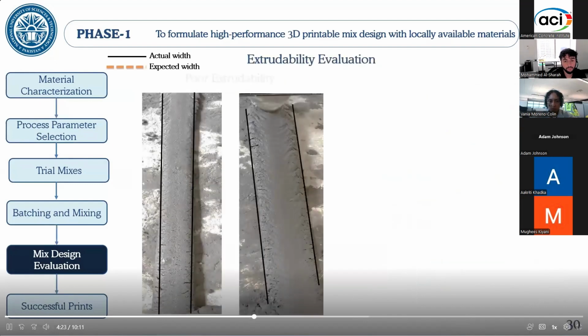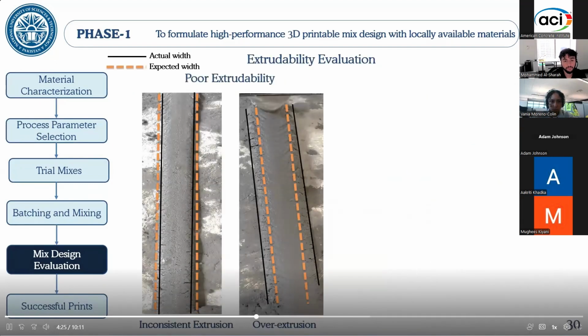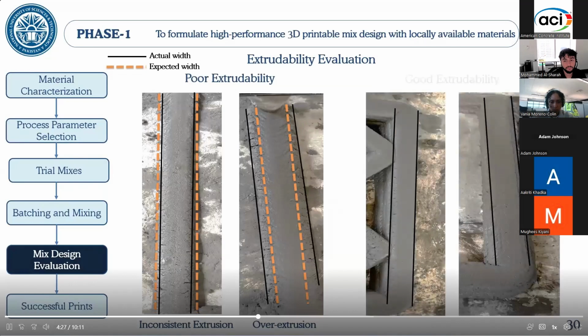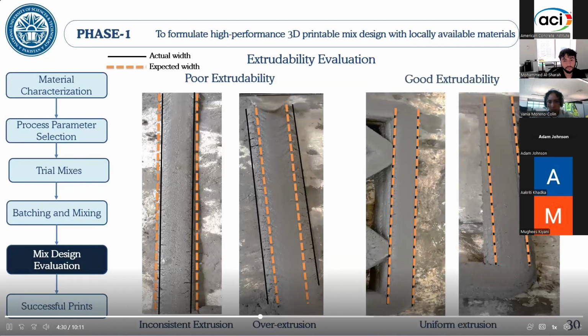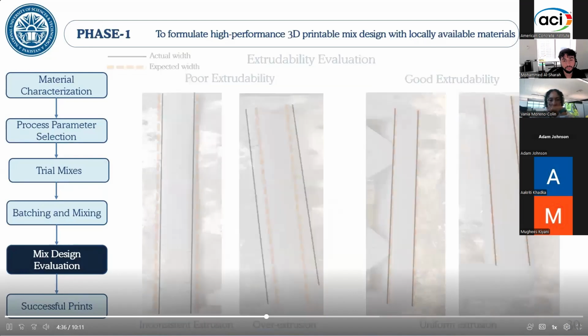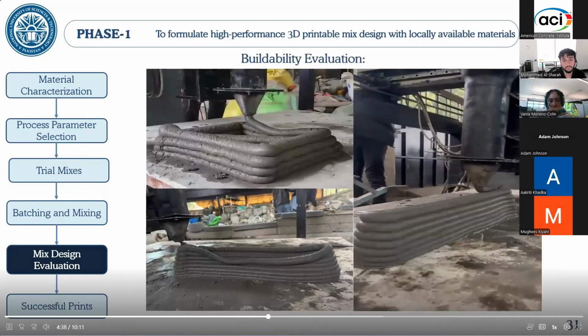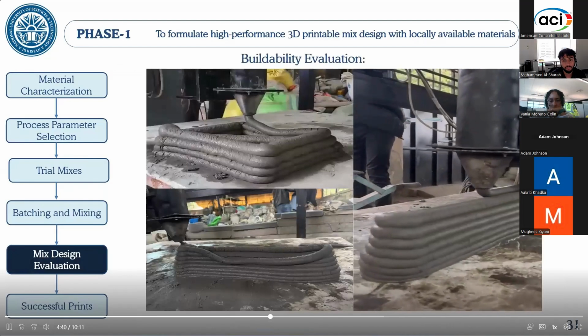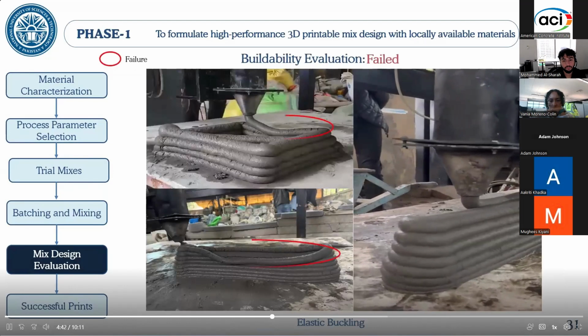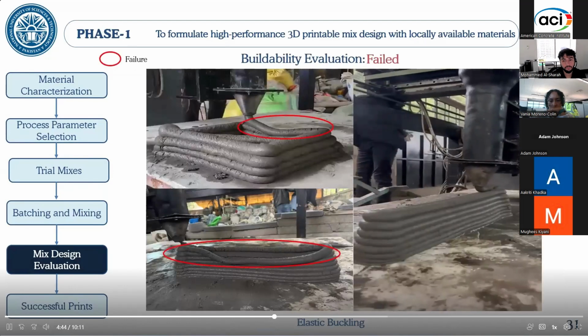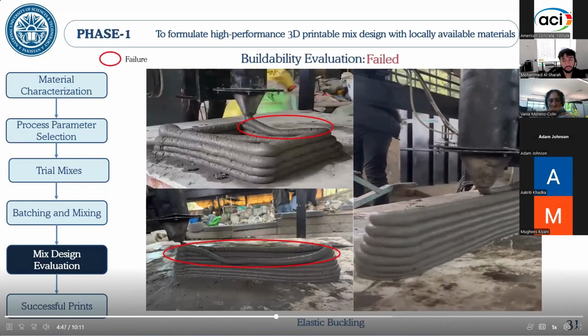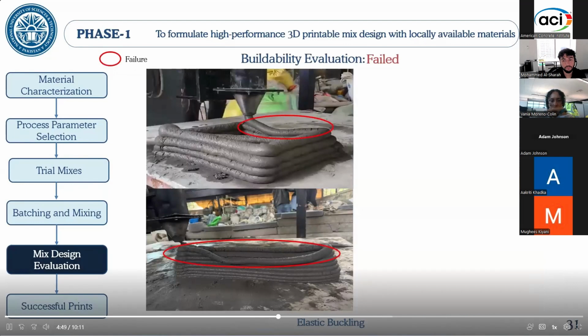These are some examples of poor extrusion. As can be seen, the expected and actual widths do not match, while these two on the right are examples of good extrudability as the expected and actual widths do match. Moving over to another fresh property, buildability. The upper layers of these specimens have collapsed due to elastic buckling, which occurs when interlayer instability is present, and that happens when the stand-off distance is too great.